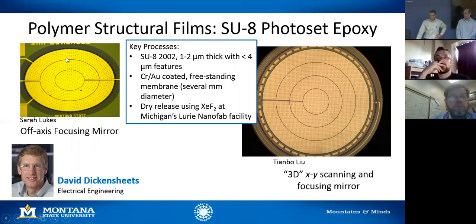You'll notice there are little features patterned on the surface. We've developed recipes that allow reliable patterning of 4 micron holes through that SU-8. We use those little holes to subsequently etch the silicon from underneath so that we leave a freestanding thin film of SU-8. This is gold coated; the shiny part you see is gold on top of the membrane. But we don't have the dry etch chemistry here at the MMF to do this final etch step.